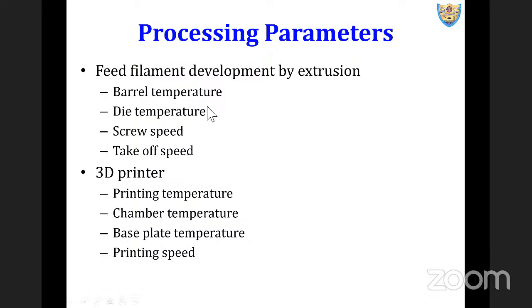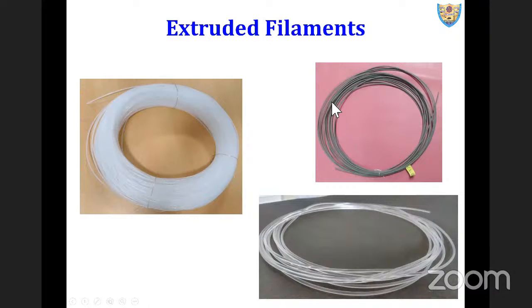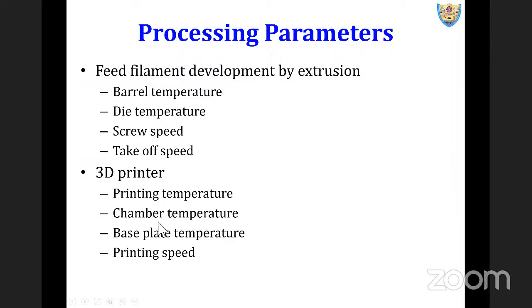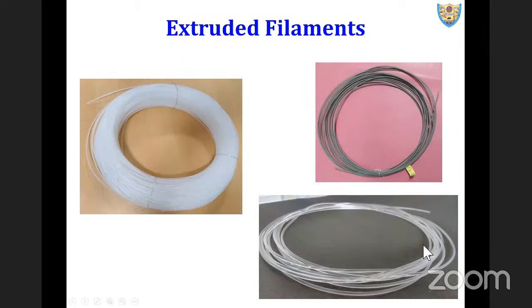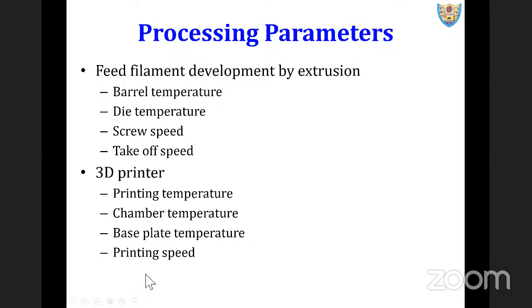Once you have the filament, which you can see here, this is the extruded filament before sending it to a 3D printer. This is of HDPE. This is HDPE with fly ash cenosphere. This is an elastomer filament which we also extruded. Then we feed these filaments to a printer, wherein printing temperature, chamber temperature, base plate onto which you deposit the material, and the printing speed need to be tuned.